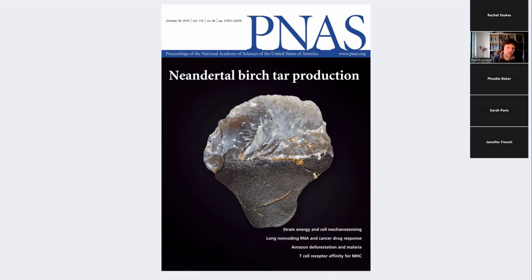It was radiocarbon dated to be about 50,000 years ago, towards the limit of what could be detected with radiocarbon. And again, it was chemically analyzed and identified to be birch bark tar. We hypothesized, based primarily on the yield, that it was a large amount of tar, and we knew from the previous experiments which methods were more efficient than others, and that the environment at the time this was made had very little woody material around. So we hypothesized that Neanderthals were likely using one of the more complex methods of producing tar.